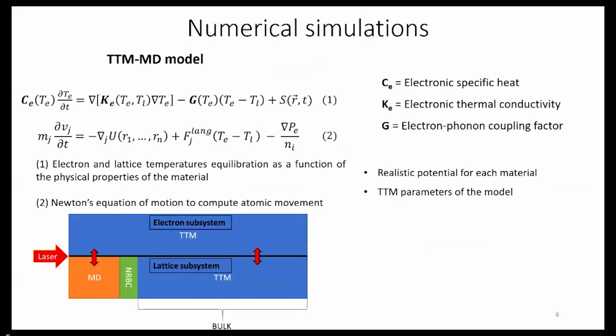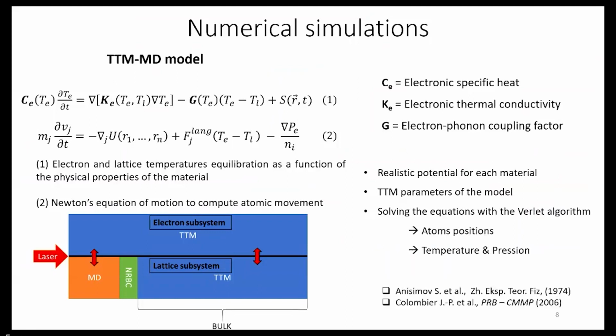To implement this, we need some parameters for the TTM model, which are the electronic specific heat, the electronic thermal conductivity, and the coupling factor between the electrons and the phonons. We also need a realistic potential, which is adapted to this use. Then we solve the equations with the Verlet algorithm, and we get as an output the atom positions as a function of time and space, and we can compute the thermodynamic variables.